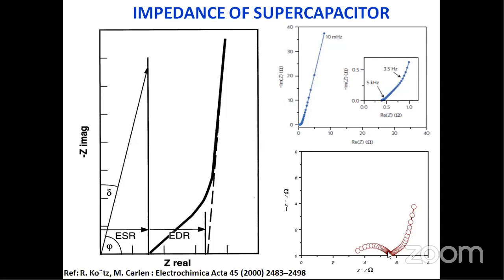Here you look, this is a semicircle, diffusion and the surface reaction. From that impedance we can directly find whether this is a diffusion process, or which one is dominant, adsorption or surface reaction. Of course we can find the ESR value as well as the solution resistance as well as the charge transfer resistance. You can fit the electrochemical impedance spectroscopy with some models or software and find the equivalent circuits, where the solution resistance is, and how the combinations of capacitance and resistance are.